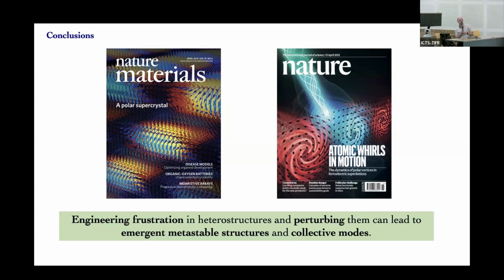And that competes with the electrostatics, which actually is worse in the 3D supercrystal. Is that correct? Right. So both are important. Elastic and electrostatic are both important. So the elastic strain goes down, and the electrostatic strain actually goes up because you saw all those vectors are doing all sorts of things. So they are going to build up some charge, and the electrical energy actually goes up. But the elastic energy goes down more than the electrical energy goes up, and so it's still good. It prefers that. Thank you.